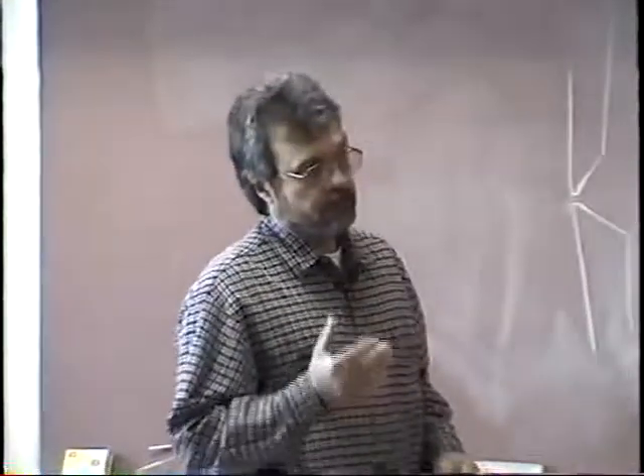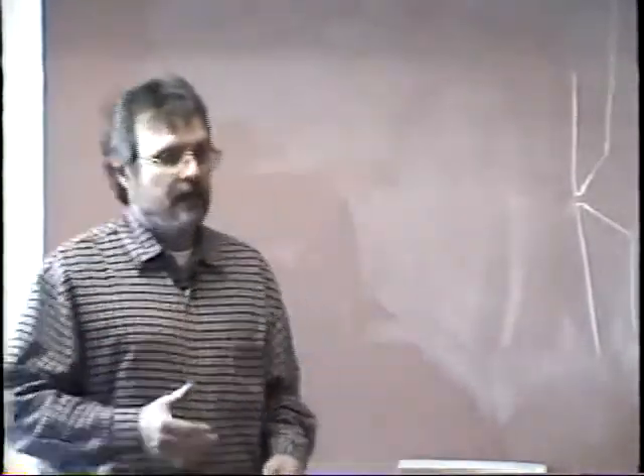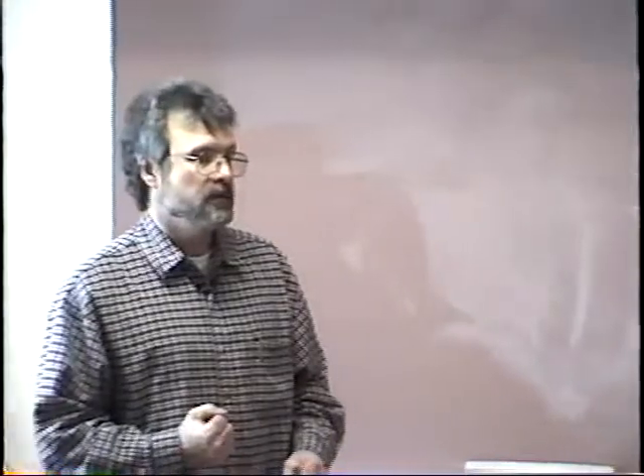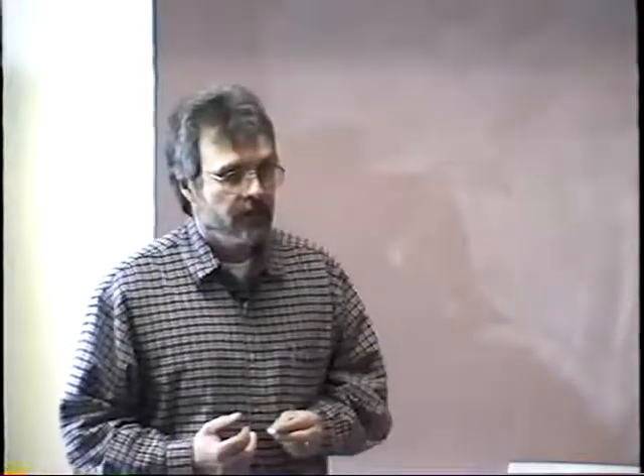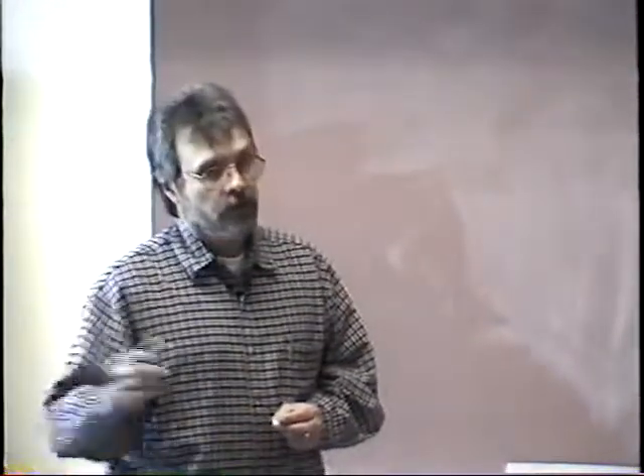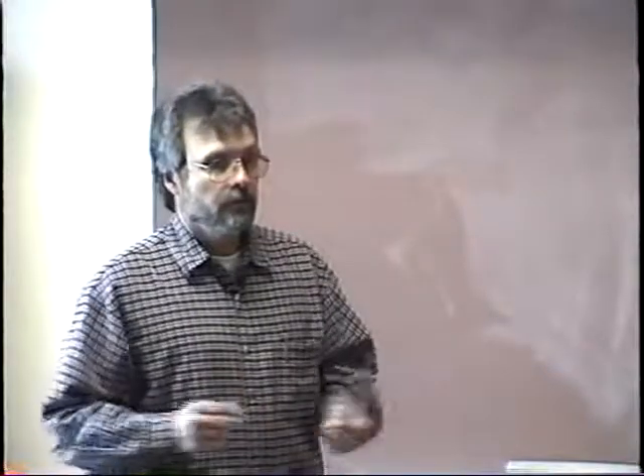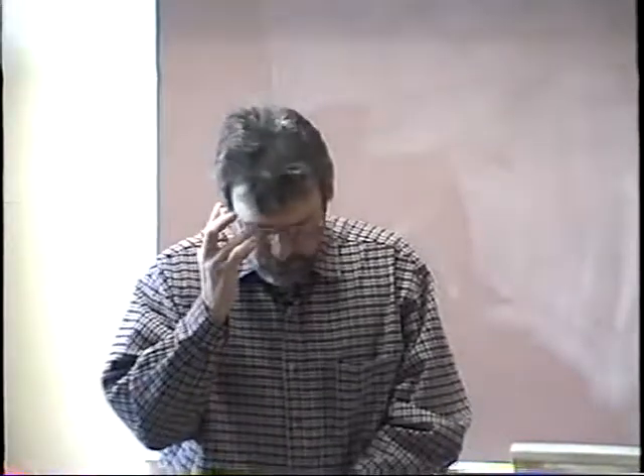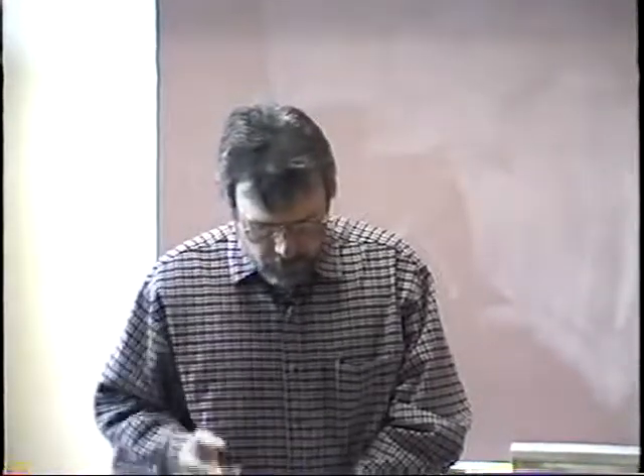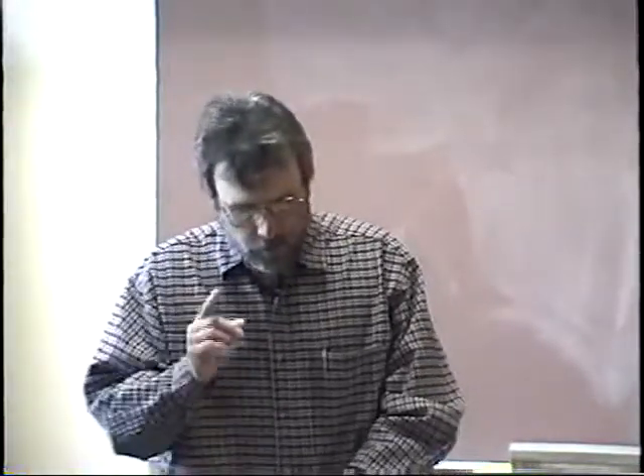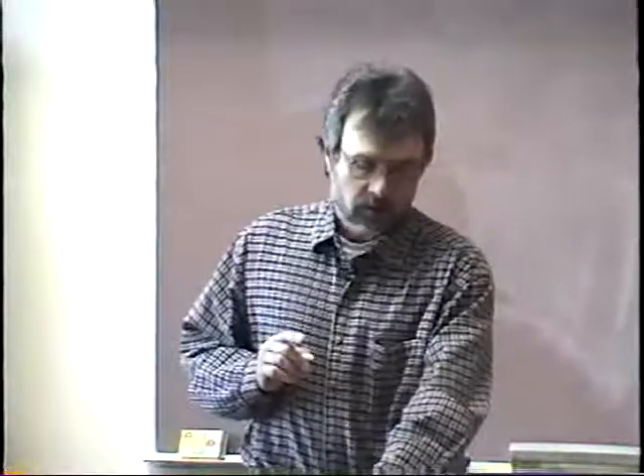Personally, if I'm making a weld and I see that I'm not getting penetration because that land is too thick, I'll use the softening technique, or I'll turn up my amperage, or maybe a combination of both. Okay? I wasn't going to cover root bead with low hydrogen electrodes, but I will tell you this: one question comes out of that section.